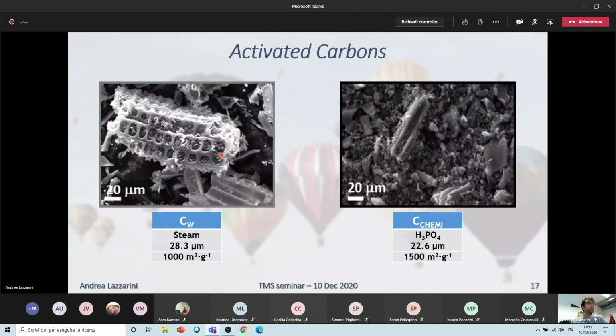So I was working mainly on activated carbons produced from pine wood, so basically ashes of trees. As you can see in this picture, it's still possible to observe the walls between the cells that were composing the lignin structure of the tree. And these two carbons come basically from the same kind of vegetable, but they were treated in different ways. One was impregnated with phosphoric acid, and one was treated in steam at high temperature, basically 1000 degrees in the absence of oxygen. They present very similar granulometry of the particles, and they both have high surface area values.